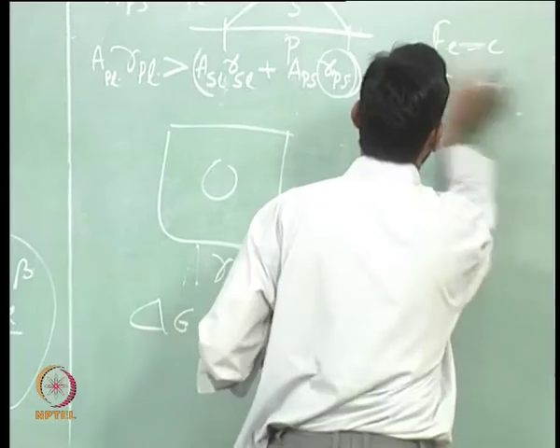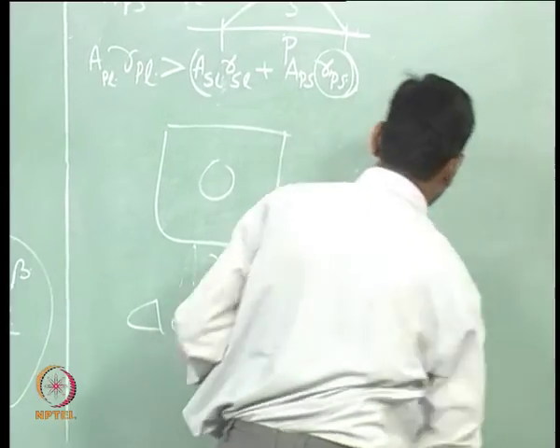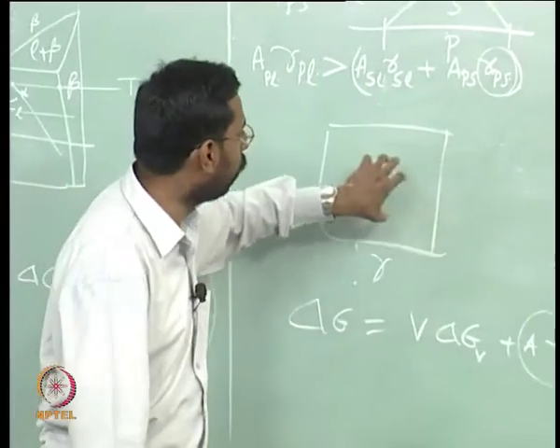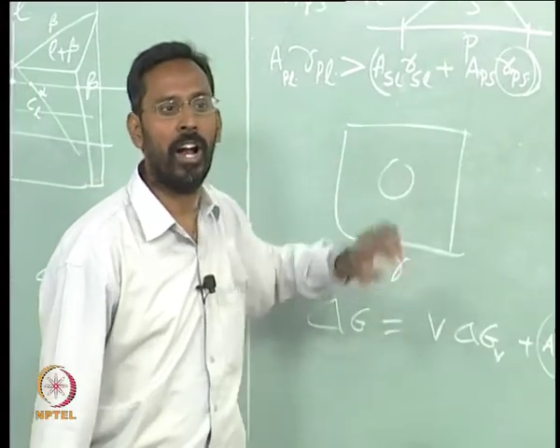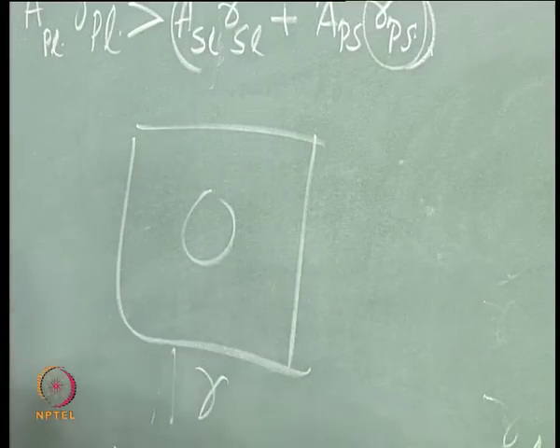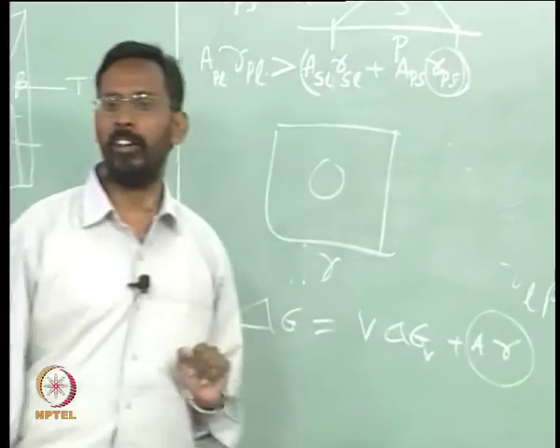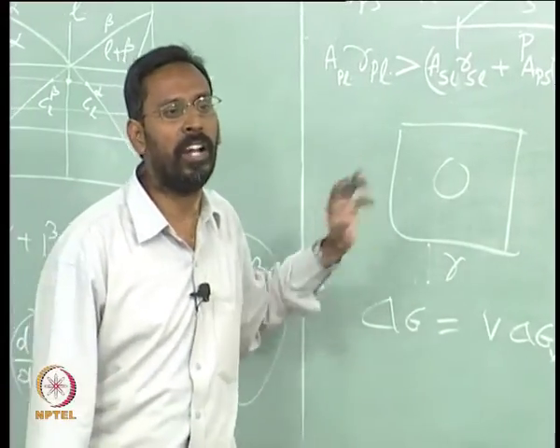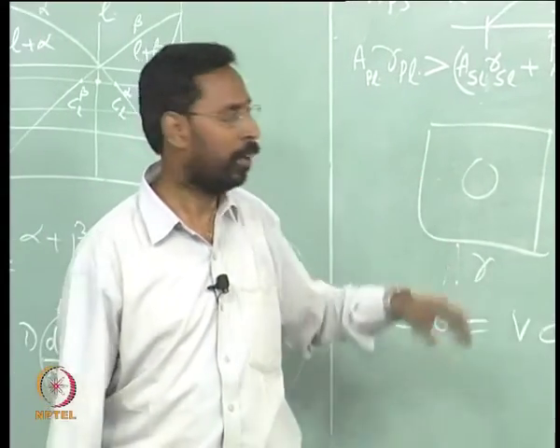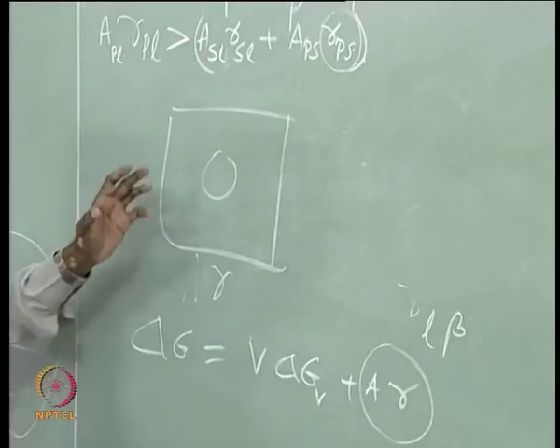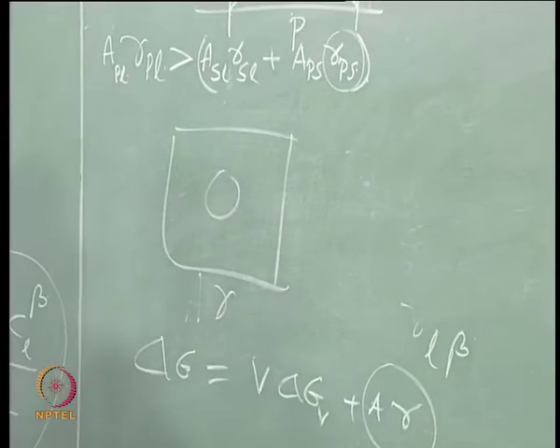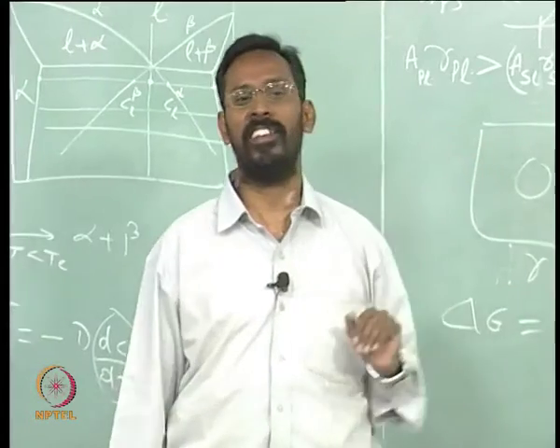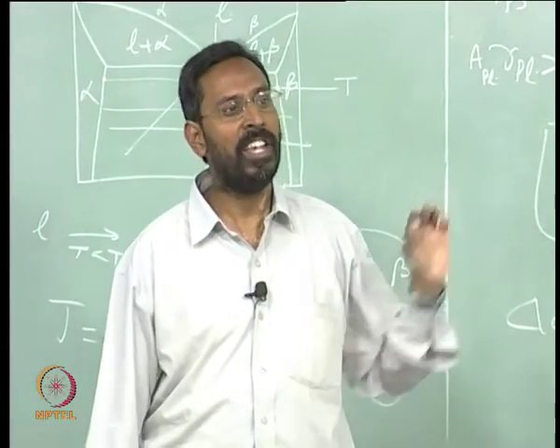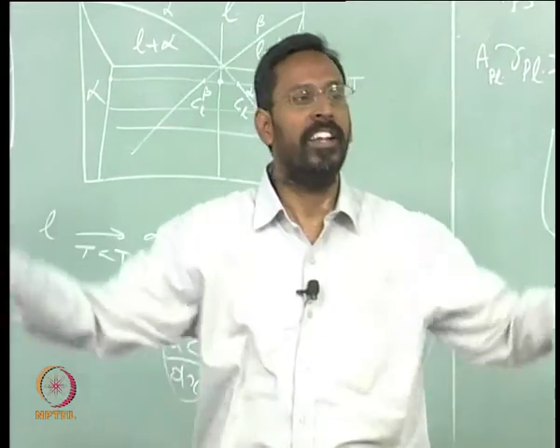Coming back to the point - it would be alpha that nucleates and grows, and then the rest becomes beta. In the other case, where liquid-beta interfacial energy is lower, you will see beta nucleating and growing instead. So depending on the situation, you get different morphologies of alpha, but you will always see that there is no lamellar nature - you will always see one phase growing inside the other.